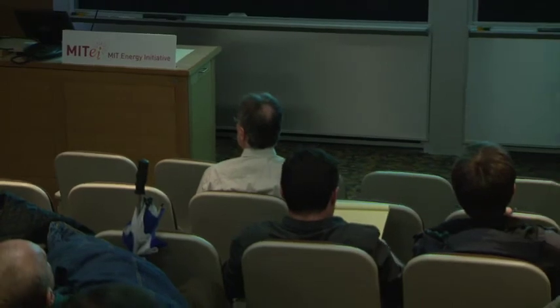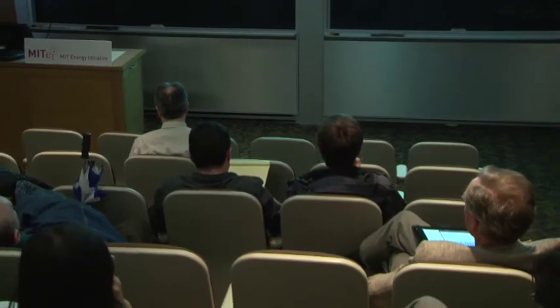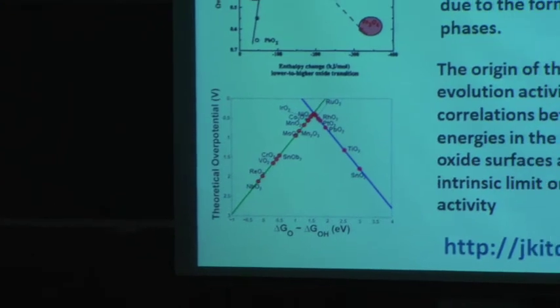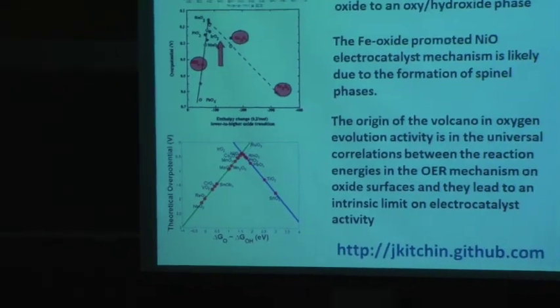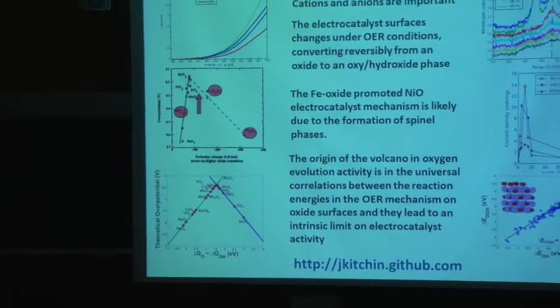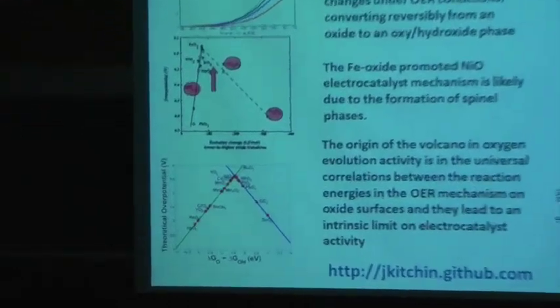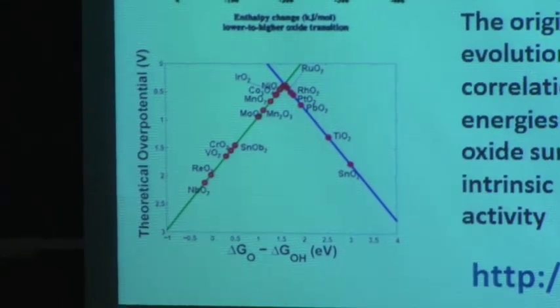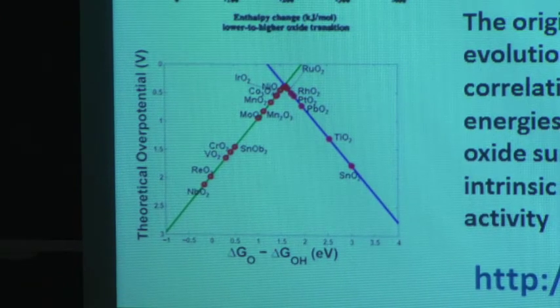Yes. And on your computer simulations, you mentioned that none of the materials that you examined were optimum. They were off that scattergram that you showed. Were any of the materials that you looked at potentially worth testing in the lab and maybe theoretically better than the standard plain nickel? Yeah, so unfortunately all the standard candidates come up here, iridium oxide, ruthenium oxide. Okay, so they're already at the top, so we sort of confirmed that those should be the best ones. So that part of the model works, and so where we've tried to refocus our energy is, taking nickel oxide and cobalt oxide are, for details that are important but not real interesting, in the wrong place on this diagram because of errors in the DFT calculations.